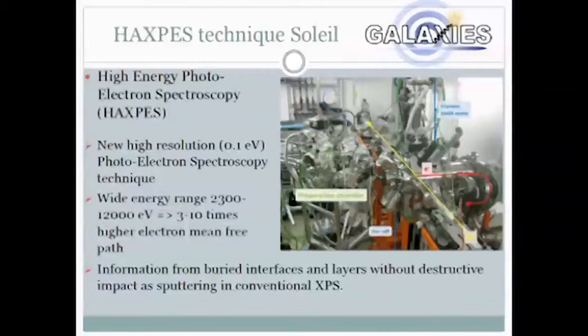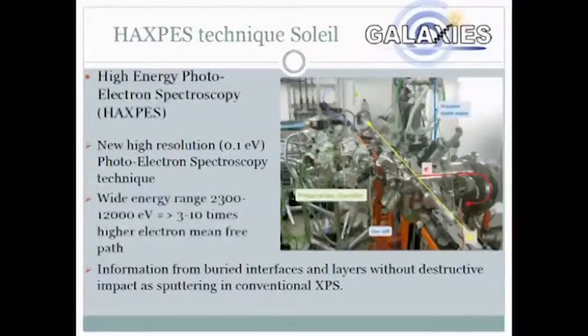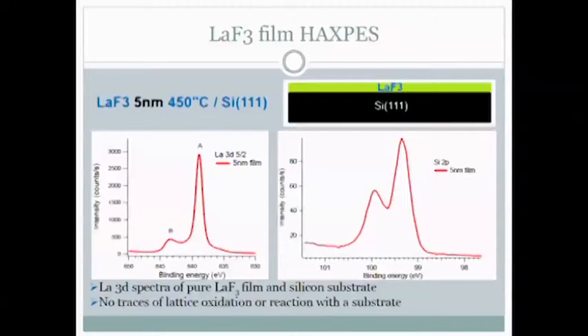These films were studied in state of the art. We've got the possibility to use beam time at the Soleil synchrotron near Paris, which is mainly the same as X-ray photoelectron spectroscopy, but with higher energies. So we've got a high energy light beam, which goes on top of the substrate, and then electrons are emitted from the surface, and we could analyze these electrons with an electron analyzer, and the electron energies give us a sort of fingerprint of the material, as you could see on the next slide.